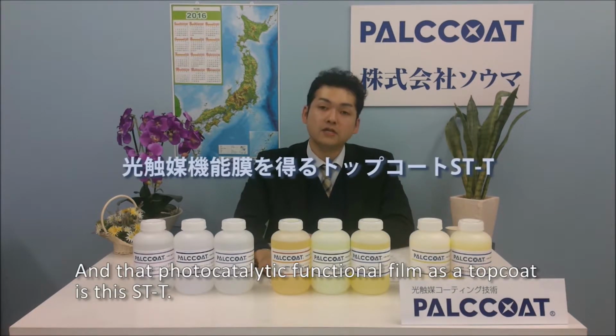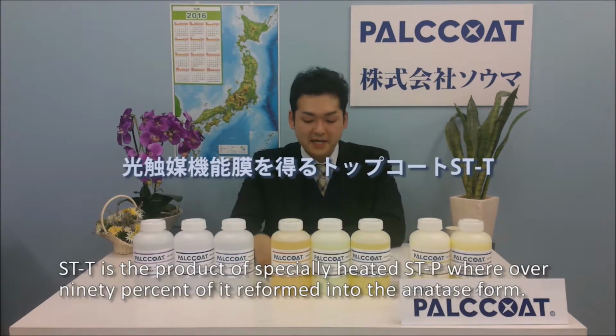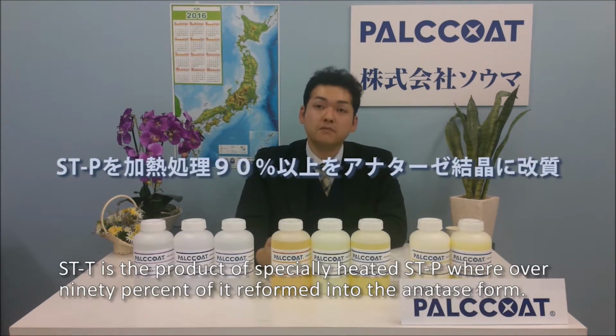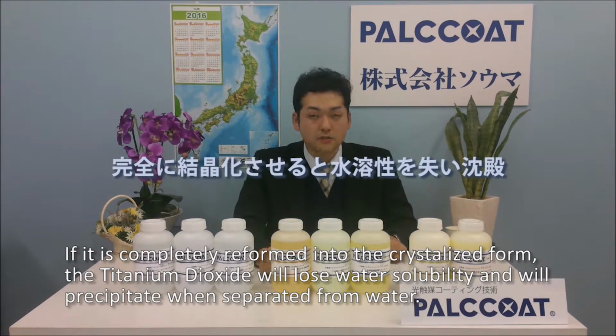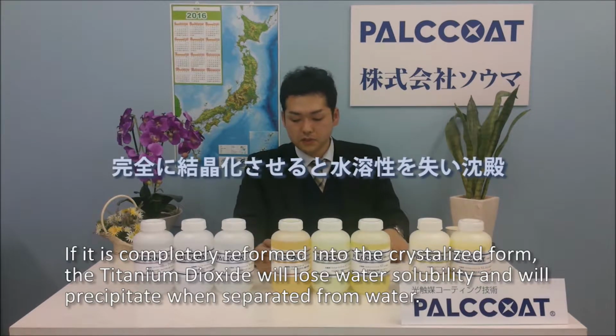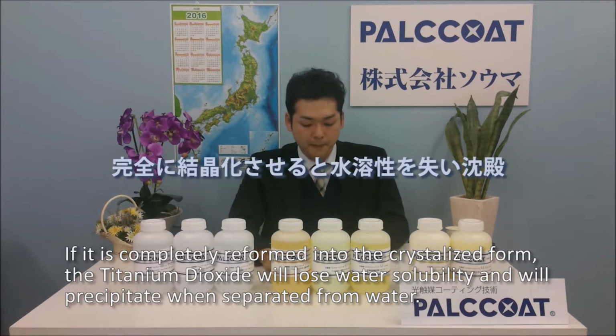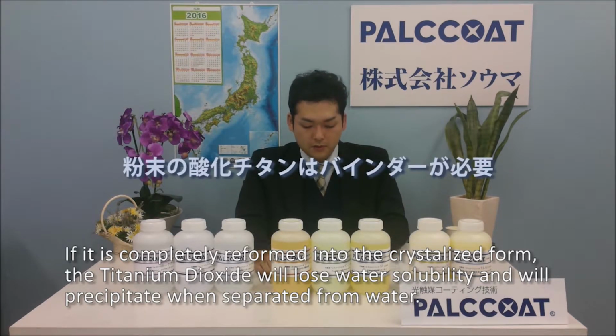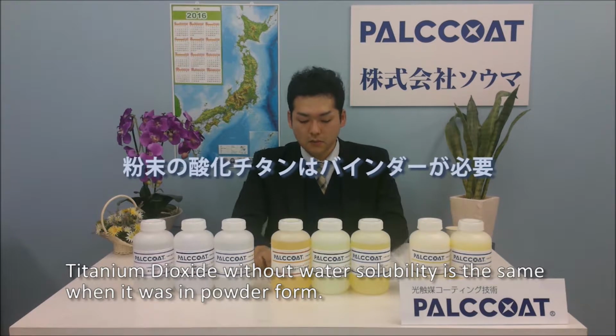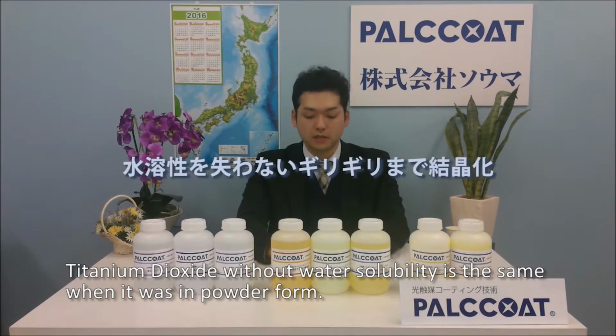And that photocatalyst functional film as a top coat is the STT. STT is the product of specially heated STP where over 90% of it is reformed to the anatase form. If it is completely reformed into the crystallized form, the titanium dioxide will lose water solubility and will precipitate when separated from water. Titanium dioxide without water solubility is the same as when it was in powder form.